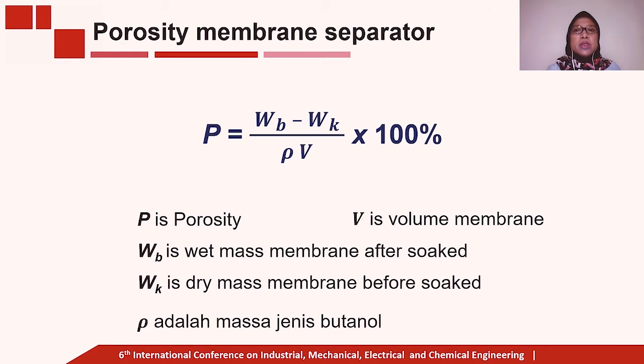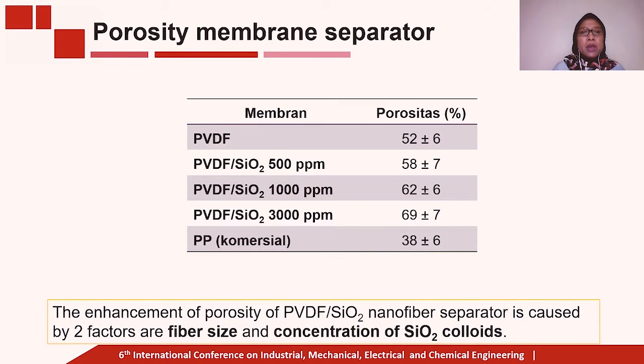Next is porosity membrane separator. This is the equation to calculate the porosity, and this table shows to us that the porosity increase after SiO2 addition. Increasing the membrane separator porosity due to the morphology of SiO2 structure is a porous material, making it possible for electrolyte absorption to occur in pore of SiO2 material.